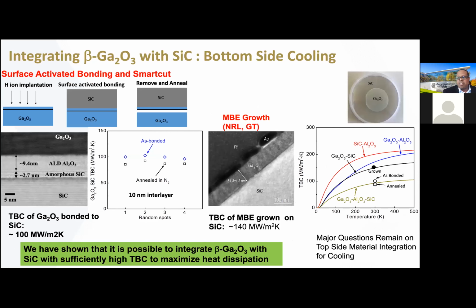And then again, you start looking at contacts. So these metal contacts here. So here we've actually been able to do the same plasma activated bonding, taking gallium oxide thin layers, transfer bonding it over onto silicon carbide. And we've also been able to do this with diamond. And then you could also look at direct MBE growth on silicon carbide. And this actually gives you a slightly better interfacial thermal resistance of gallium oxide growing directly on silicon carbide than even the bonding because of these interfacial materials.